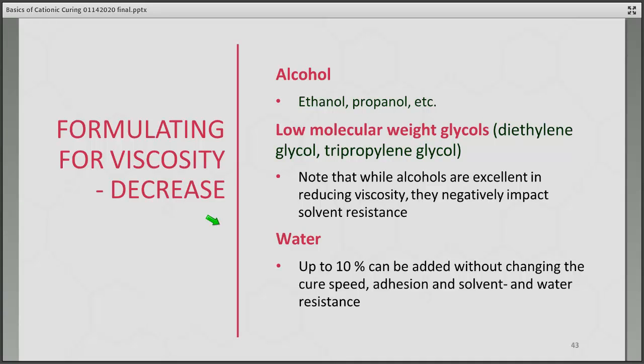You can also add alcohols, and alcohols, like a typical organic solvent, will really cut that viscosity down. So you wouldn't use a lot, depending on your system. The amount could be just a few percent, up to the 5–10% range. You use low molecular weight glycols, such as tripropylene glycol or diethylene glycol. Alcohols are also really excellent in reducing viscosity, not to mention lowering cost. They negatively impact solvent resistance. So if you're in an application that requires this, you would probably want to avoid alcohols as diluents if you do need to use diluents.